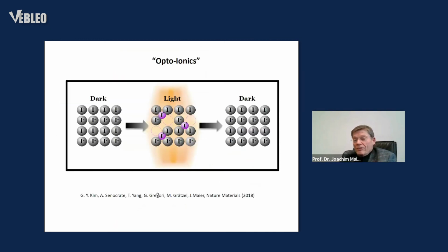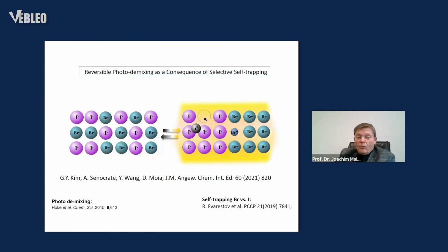What came to our surprise, and this is important to mention, is that obviously not only the electron conductivity can be enhanced by illumination, but we found surprisingly that also the ion conductivity can be enhanced. And this is our explanation. The hole is an iodine 0 essentially, and the hole may be trapped. If the hole is trapped in the iodine, then it can go to interstitial sites. The iodine 0 is much smaller than the iodine minus and can be further stabilized, and then you form vacancies that you did not have before in the dark, and they may be the source of the high ion conductivity.